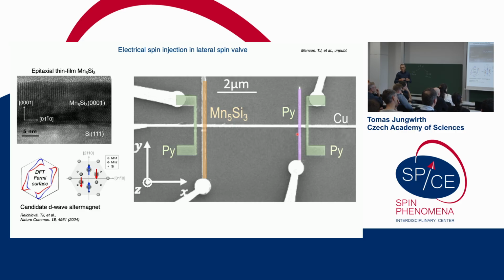That motivated our colleagues, experimentalists, to put these ideas to the test. So this is the first experiment I'd like to talk about, an experiment done in manganese-5 silicon-3, which is a compensated magnet. But when you have it in thin films, there has been indirect evidence, both from experiment and from theory, that it might be an altermagnet with this characteristic D-wave altermagnetic type of order, or D-wave Fermi surfaces.